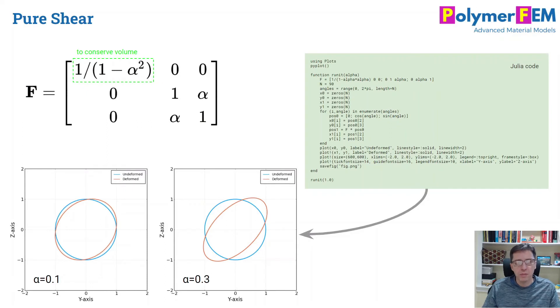Let's take a look at pure shear first. The deformation gradient in pure shear is defined here on the top. What's interesting about deformation gradients is that it really is a linear transformation of a material. So I can apply a pure shear deformation gradient on a circle. If I have an undeformed circle in blue here, what happens is that this circle will deform into some different shape. That's the red shape here. It becomes an oval, as you can see.